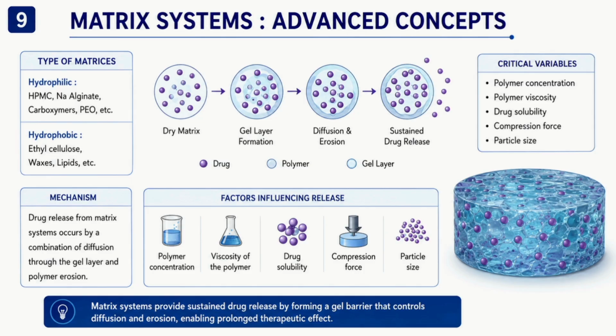Next is the hydrophobic matrix. In hydrophobic systems, materials such as ethyl cellulose or waxes create a water resistant barrier. The drug release occurs primarily through pores, channels, or diffusion pathways. Critical formulation variables include polymer concentration, polymer viscosity, drug solubility, particle size, compression force, porosity, and polymer-drug interaction. All these factors need to be considered. Therefore a matrix formulation is not simply a matter of selecting a polymer. We must understand the relationship between polymer properties, hydration behavior, microstructure, and drug transport.